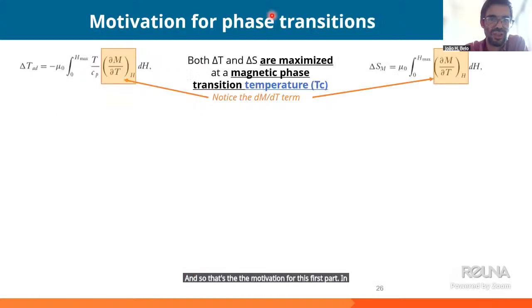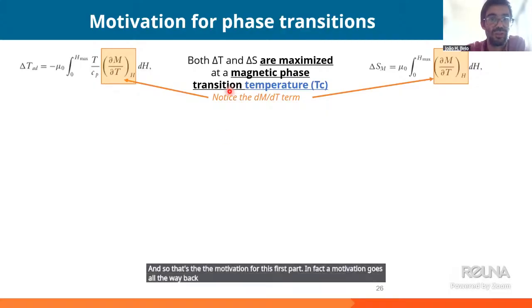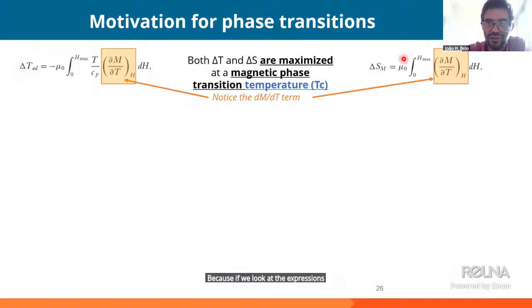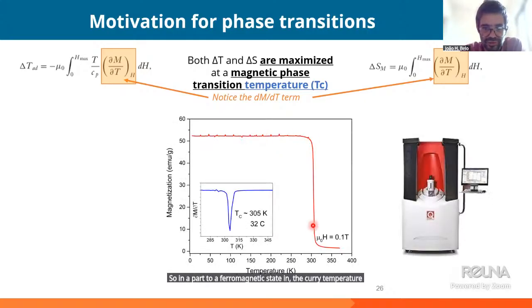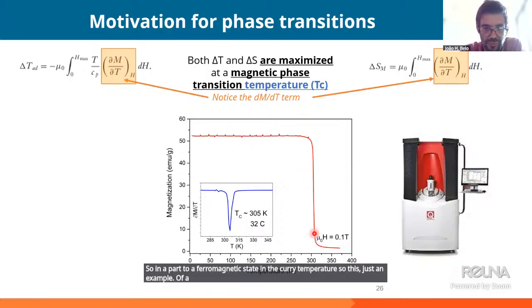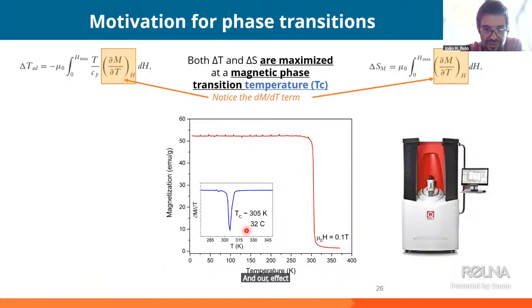In fact, the motivation goes all the way back to studying phase transitions, because if we look at the expressions of the delta T and delta S, we see a common factor in them, which is the derivative of the magnetization with respect to temperature that is present in both parameters. So this means that both the delta T and the delta S are maximized at a magnetic phase transition temperature. So in a para to ferromagnetic state, at the Curie temperature. So this is just an example of a magnetization versus temperature curve, and our effect is maximized exactly at the TC.